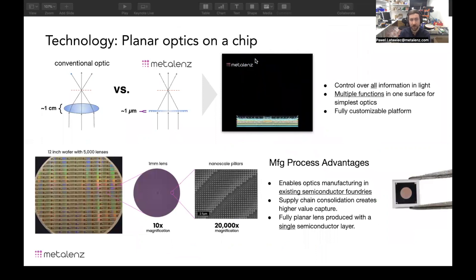The technology that we do have looks like this. If you are familiar with optics, you'll know that a typical lens has these curved surfaces which bend and refract the light. Ours is more of a diffractive optical element where the light comes in and then our nanostructures, our patterns, end up bending the light into certain directions, mostly through that nanoscale interaction with the material that we've designed or how we've chosen to array that material. What's nice is that in a typical optic, you only have access to maybe just the intensity or the direction of the light going in a certain way. We're able to actually have more knobs to turn in terms of the color, but also polarization of the light going through the optic.